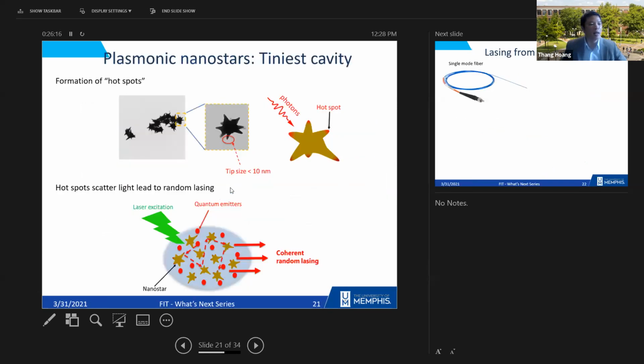And as another approach, we can also use some other structure. For example, we have a nanostar. A nanostar has a bunch of spikes, and one of these spikes is very tiny. It has a size of less than 10 nanometers. So when you hit light on those nano spikes, the light is going to get trapped in that tip, and it creates some sort of hotspot. Then if we have many of those nanostars, and we hit a laser on them, and they have some dye molecules in them, the dye molecules are going to emit some light and scatter back and forth, and that creates some sort of coherent random lasing.